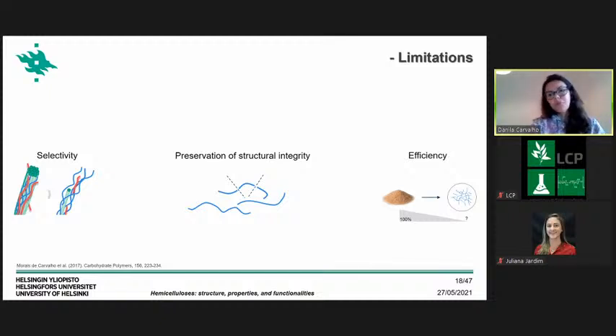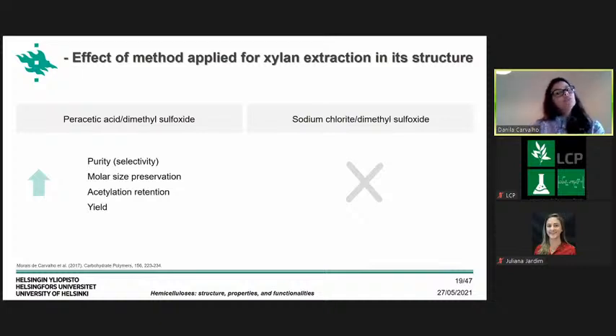And as I told you, two types of delignification were applied. One using peracetic acid, another using sodium chlorite. And what we could see from the results was that the purity, the preservation of the structural attributes, and also the yield of the method using peracetic acid were better than that using sodium chlorite. So in this study, we decided to continue only with the samples prepared using peracetic acid, followed by the solubilization of the xylan by dimethyl sulfoxide for the fundamental analysis of their structure.